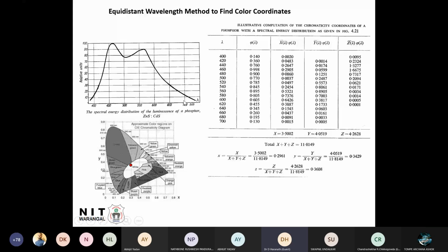I have taken a typical phosphor spectrum, and we have to normalize it to 100%, that is, to 1. The highest peak will be 1, and accordingly the intensity numbers will change for all wavelengths. Here I have taken a difference of 20 nanometers from 400 to 700, so 400, 420, 440 nanometers. For every wavelength, what is the intensity? This is the intensity, I of lambda.